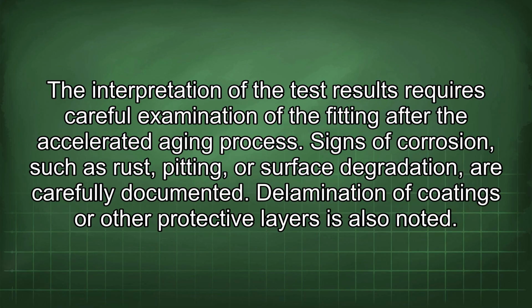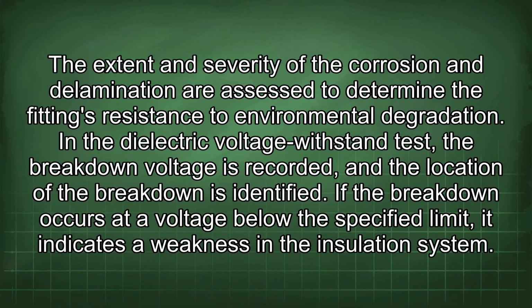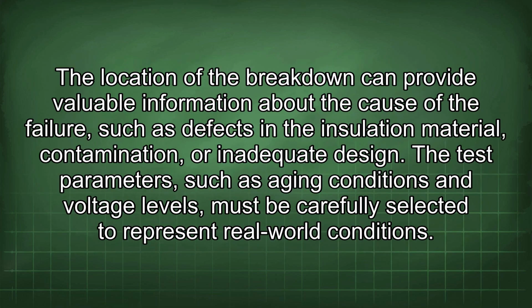The interpretation of the test results requires careful examination of the fitting after the accelerated aging process. Signs of corrosion, such as rust, pitting, or surface degradation, are carefully documented. Delamination of coatings or other protective layers is also noted. The extent and severity of the corrosion and delamination are assessed to determine the fitting's resistance to environmental degradation. In the dielectric voltage withstand test, the breakdown voltage is recorded, and the location of the breakdown is identified. If the breakdown occurs at a voltage below the specified limit, it indicates a weakness in the insulation system. The location of the breakdown can provide valuable information about the cause of the failure, such as defects in the insulation material, contamination, or inadequate design.